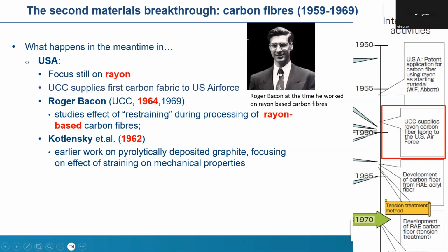In the US, we have Roger Bacon, who, after his work on the carbon whiskers, collaborated with his people in Union Carbide, and they also started, 1 year after the UK people, studying the effect of straining the fibers during the carbonization process. But they were still hooked on rayon-based carbon fibers. And this straining, in fact, was also done by, and I will come back to that, Kotlensky, another American researcher, who proved that by straining pyrolytically deposited graphite, they could also increase the mechanical properties.